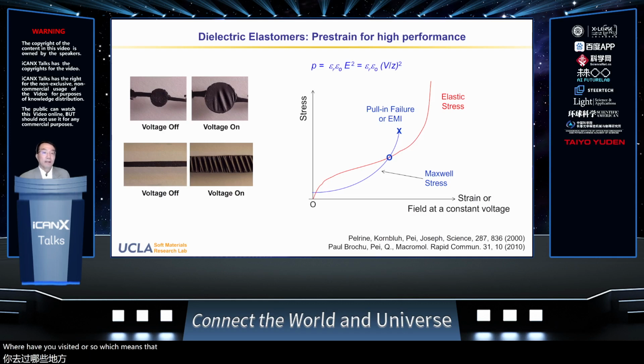Which means that at a constant voltage, when the voltage causes the film to expand, as the film expands, the thickness reduces and the field increases. Okay, so we have a positive feedback loop here: at the same voltage, the film becomes thinner because the field increases. So eventually, this positive feedback loop will cause the dielectric elastomer to reach a high strain, crossing the dielectric field strength of the polymer. So there will be a dielectric breakdown.